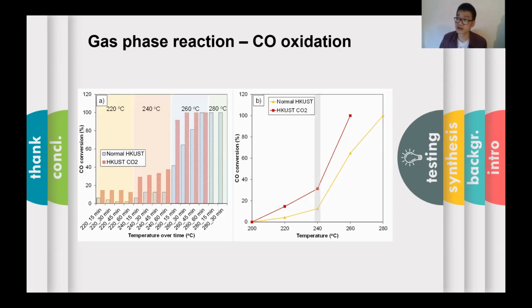Demonstrate that the CO molecules could access the open copper sites in HKUST CO2 more efficiently than in normal HKUST at these temperatures. And note that the HKUST CO2 sample has decreased surface area and a slightly lower amount of copper than the normal HKUST, which could normally have compromised the activities. So the increased catalytic activity of the HKUST CO2 is attributed to the existence of the macropores in the HKUST CO2, which was seen previously in the SEMs.